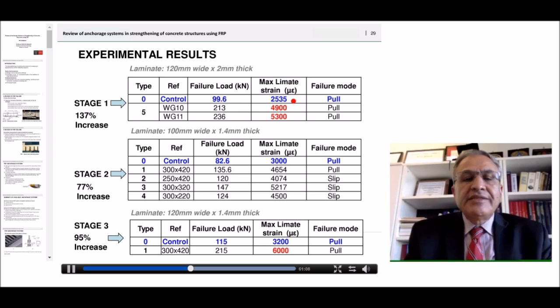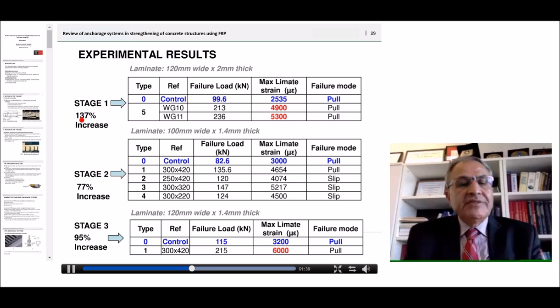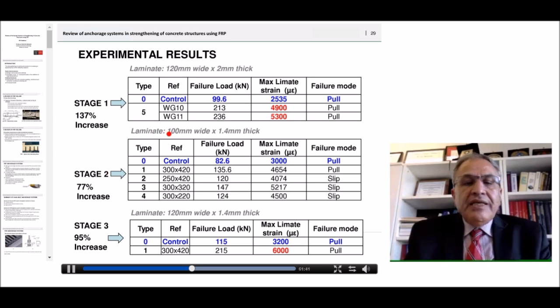0.25% or 2535 microstrain to 0.49% and 0.53%. So the failure mode was a pull of the concrete cover. So you can see here the efficiency. The capacity of the laminate increased more than double, so you have that 137% increase. And the other one, when you have got 100 millimeter wide laminates with 1.4 millimeter thick